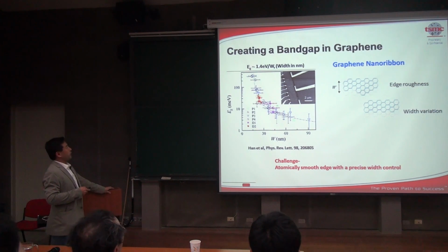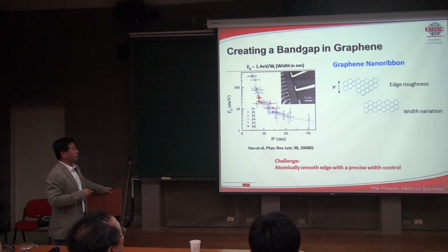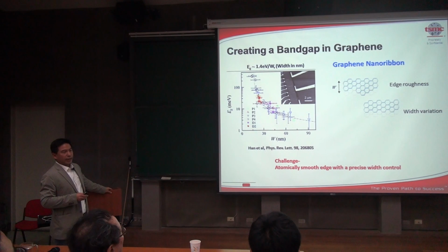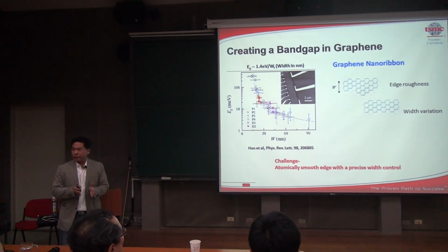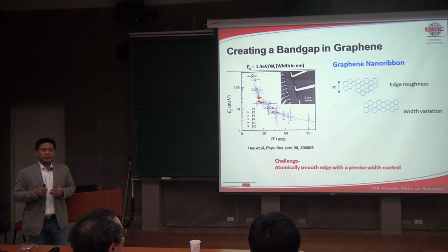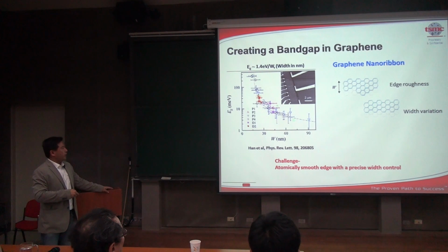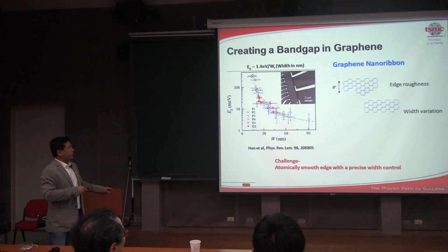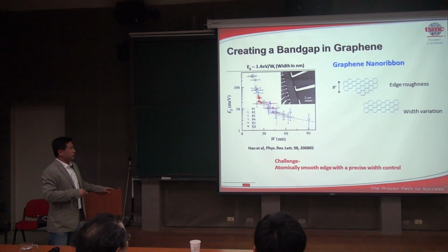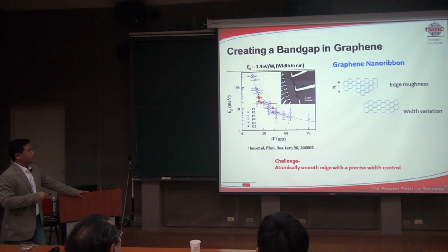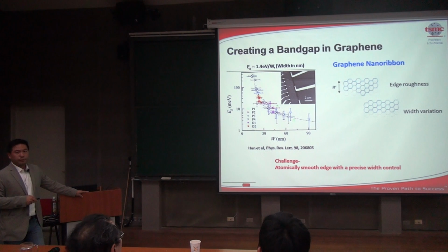Efforts also have been made to try to create a bandgap in graphene using a nanoribbon. The idea is that through quantum confinement, you can create quantum states that create a bandgap. And indeed, with some nanoribbons, you seem to have some kind of bandgap, but you can see a lot of noise, and it's still arguable if what you're seeing is really the result of a bandgap.